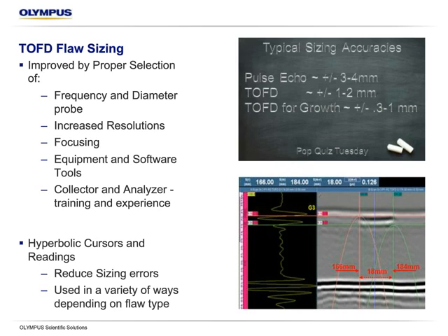TOFD is also used for growth monitoring. If you had a flaw that you had detected with TOFD and recorded its size, and then wanted to go back and monitor it, this might be an online thing where you don't want to take a pipe offline or a nuclear component offline, the sizing accuracy can be quite good, at a 0.3 to 1 millimeter typical range. Just a few different variables to consider.